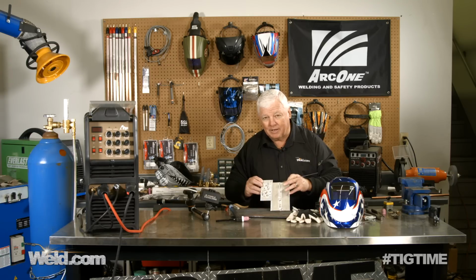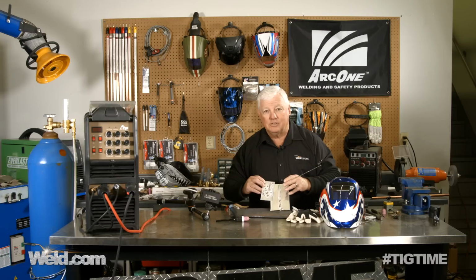It doesn't happen like when you're welding on steel. It happens so smooth, so quickly, you don't even know it happened. But a small glob of filler will get sucked up into your tungsten and then it starts thrusting oxides down on your part. And that's all that is. It doesn't get any better. When you have that happen to you, and I'm going to show you how it happens and what it looks like, you got to get rid of that contamination, and you can't grind it off. Typically, you have to break it off. So let's show you what that's all about.